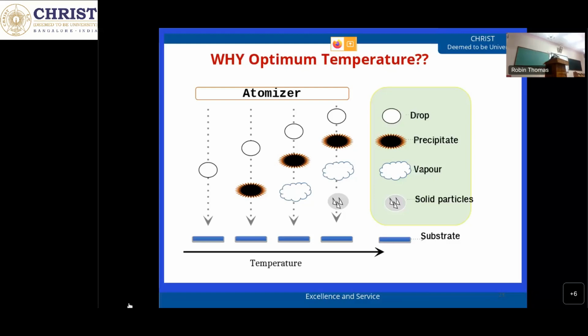You talked about the efficiency, right? And you talked about, if you rearrange the layers, the efficiency can be increased. Do you have a number for how much efficiency can be increased? If I say about myself, when I first fabricated, it was like 0.1% efficiency. Then I tried stacking different layers. So top layer and block layer increased my efficiency to like 1%. But the sandwich layer didn't work for me. Then I changed the thickness. When I increased the thickness of the buffer layer, I didn't get much improvement in efficiency. But when I changed the thickness of the absorber layer, I could reach almost 4%. In the case of thin films, that's very good efficiency. So from what I first got, when I got a device, I modified the structure to increase the efficiency. That's why I explained that.